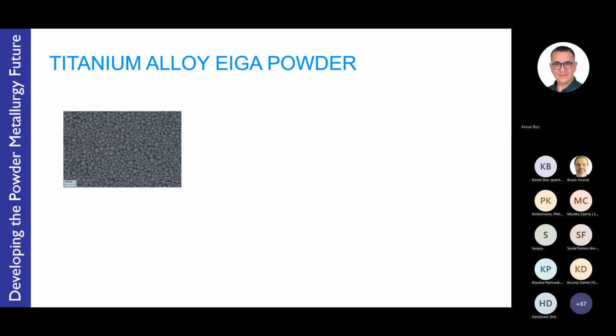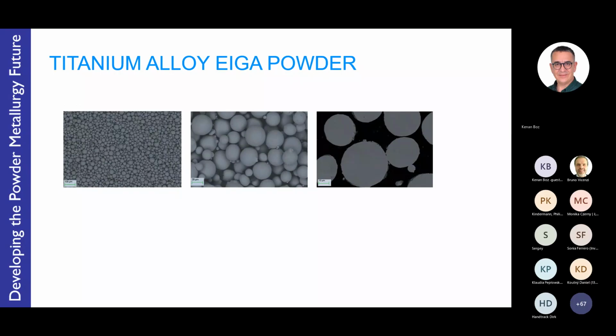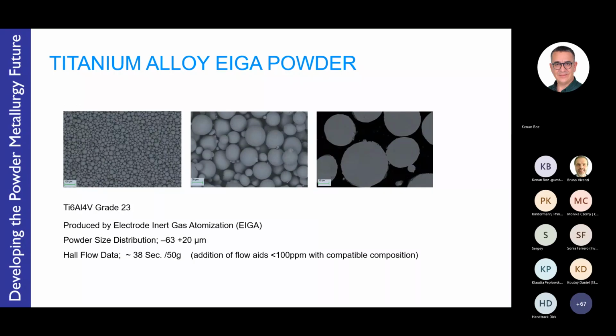And what does the titanium powder look like? A very spherical powder, actually, and has a range in this case of 63 to 20 microns, and good flow characteristics. Of course, titanium has a relatively low density, so flow is impacted by its density as well as its morphology. In this case, it has recorded a Hall flow result of 38 seconds for the 50 grams, but this was with the aid of a flow aid.